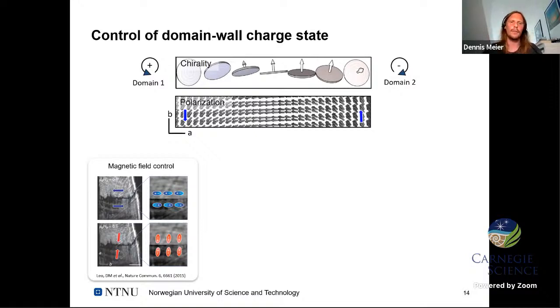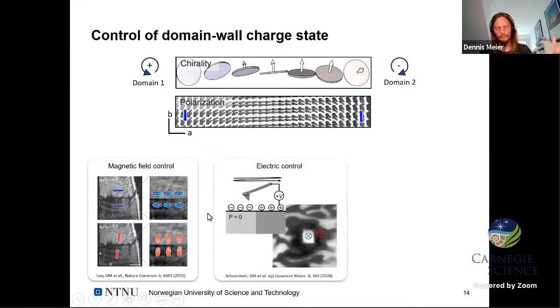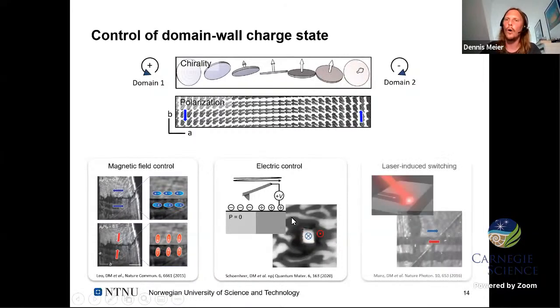What we showed in manganese tungstate, for example, is that you can apply in these type of materials a magnetic field, and by applying the magnetic field, rotate the magnetic system, and along with that, the polarization direction. So you can play with the charge state of the ferroelectric domain walls, going from neutral to charged back and forth. You can also, for example, use electrostatic force microscopy or electrical means to switch domains and control the antiferromagnetic order that was then in a system terbium manganite. Or you can also use laser-induced switching and control electric or magnetic order and the domain wall structures using light. These are just some examples which arise due to the strong correlation between electric and magnetic order in these improper ferroelectrics. That was just to give you an idea about the added functionality.